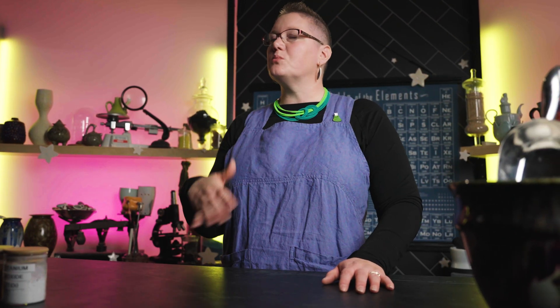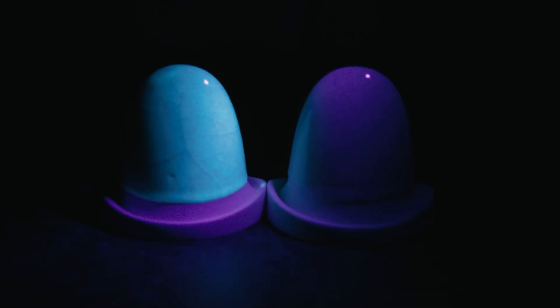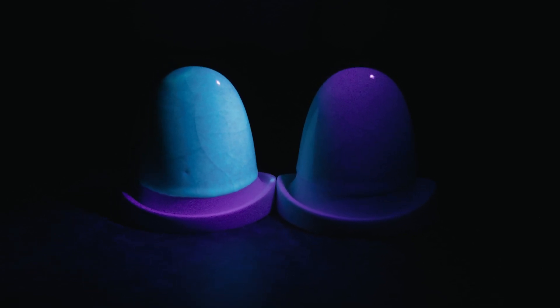To get a good melt, we found a base we're pretty happy with — we wanted a nice smooth glaze. I know a lot of you are going to be disappointed that this glaze is not going to work at cone 6 or cone 10, but that's the way the cookie crumbles. These glow-in-the-dark powders literally cannot withstand any hotter temperatures. This is the same glaze fired to cone 06: there are in fact two tiles from the same glaze batch — one fired at cone 08, the other at cone 06 — and cone 06 just destroyed the colorant. The color effect is completely and utterly gone, and that's only 46 degrees C hotter. Any higher temperature than cone 08 kills this glaze dead.